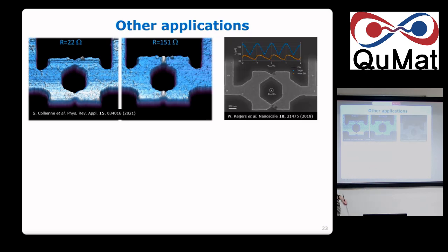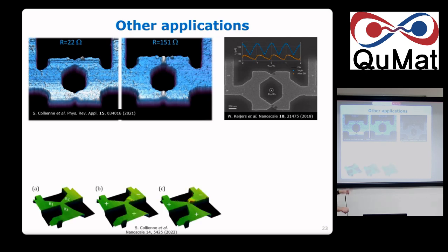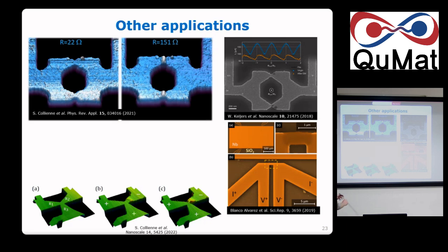We did that in aluminum as well. We work with 3 junctions, and you can select which one you want to change. No problem at all. You combine two currents that build up together, so these two are below the electromigration threshold and this one is above, and then bam, you do exactly what you want. In the top one, yes, you're adding material and increasing the resistance. You are destroying superconductivity there.